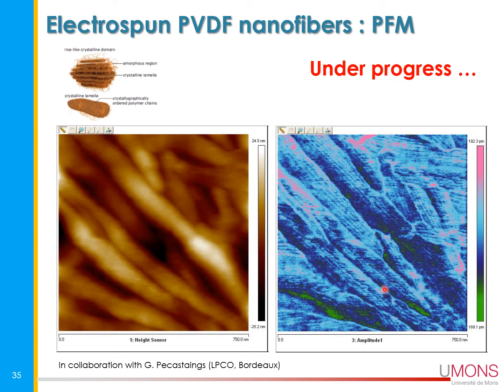You can see this is the amplitude in this case. You can see some blue lines, dark blue and light blue, most probably corresponding to the PFM signal out of these fibers. This is work which is still in progress, but we would like, instead of measuring the PFM signal on one point, to map those properties. And when we have those maps, we can play with the voltage once we have recorded those butterfly curves, and this is the data cube analysis, so we can see the behavior of these fibers depending on the voltage that you are applying to measure and to establish this butterfly shape.